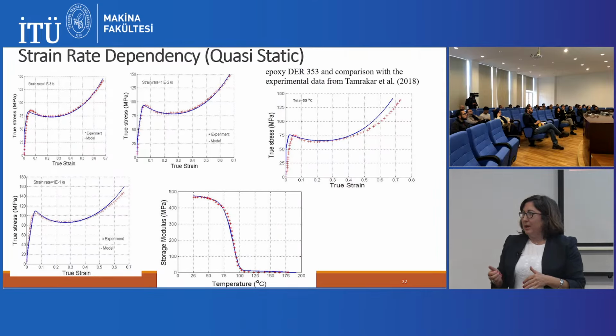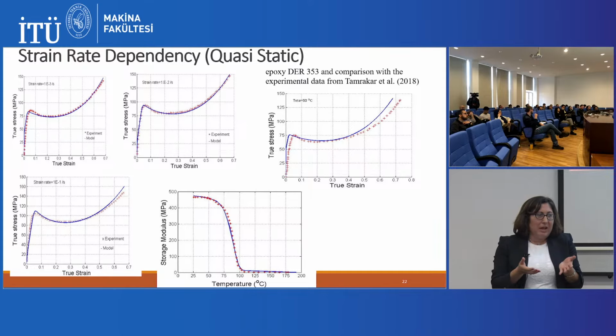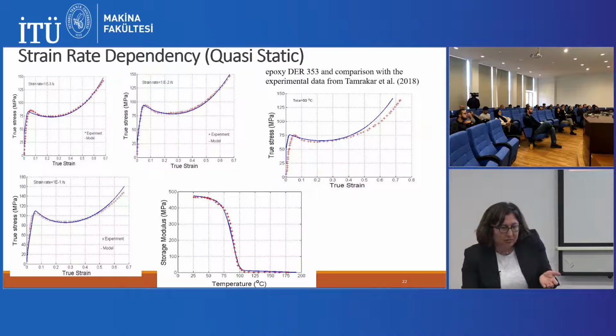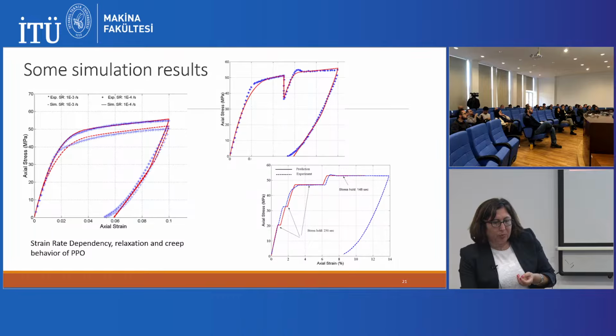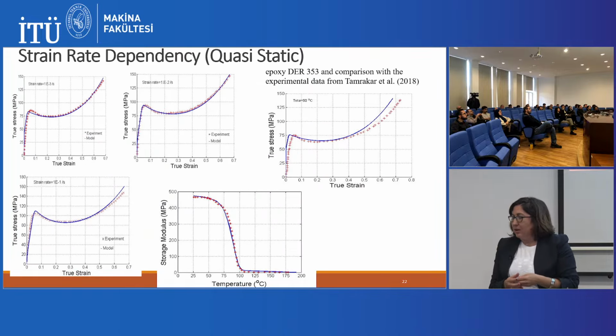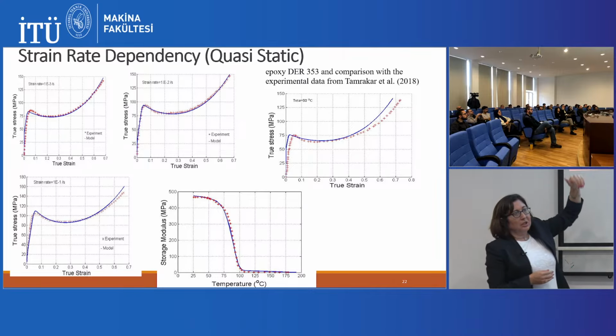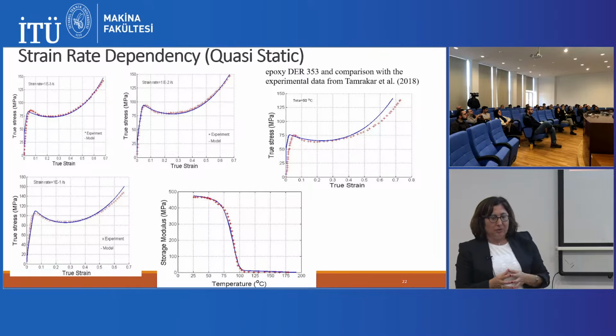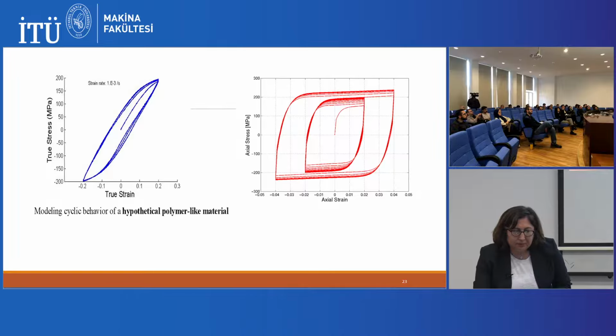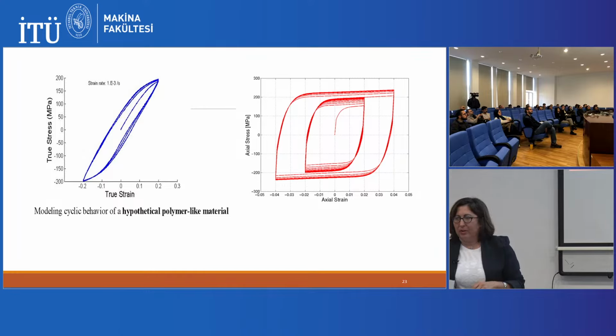What is also interesting in polymers is that behavior is not just one type of behavior. For instance, in metals, it is linear elastic, then hardening, that's it. But depending upon the material, polymers behave differently. For instance, this one is PPO. The behavior of PPO is something like this. Epoxy's behavior is something like this: some linear behavior, yielding, softening, and hardening. So these are different behaviors that we observe. And with this model, we are able to capture all this rate dependency and temperature dependency as well. This is for a hypothetical, made-up material. I also showed some cyclic loading. We are able to capture it as well.